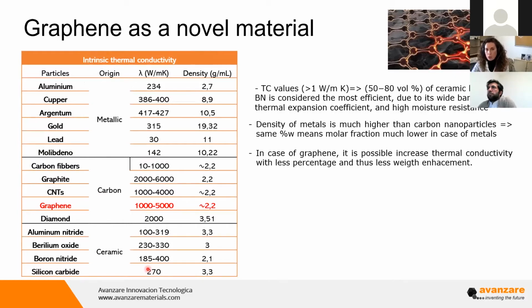But not only this. For example, it's typically assumed and published in different papers that for thermal conductivity values of about 1 watt per meter Kelvin, some loads are needed. For example, boron nitride, which is the most efficient in case of ceramic ones, needs about 50 to 80 volume percent to increase up to 1 watt per meter Kelvin. So it's a high quantity of load. In case of graphene, not only can we reduce this quantity, but I also want to remark on the difference.